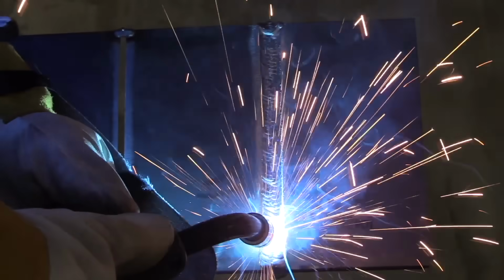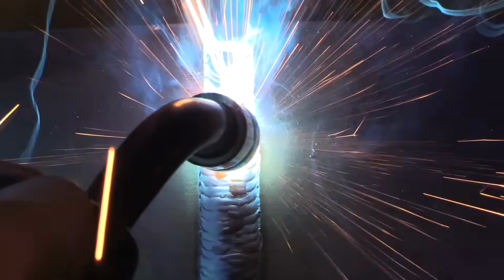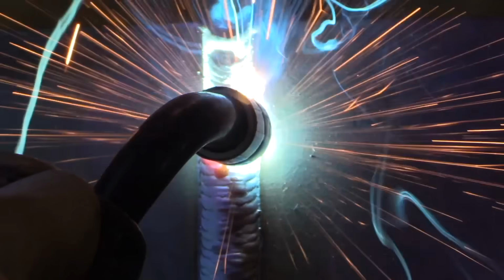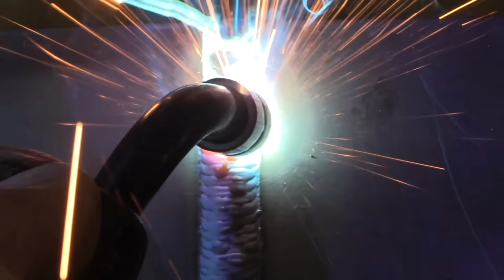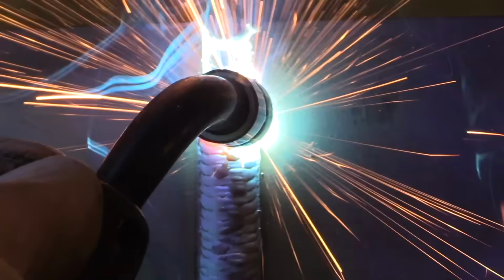But basically you're just scooting across the middle, not spending a lot of time, and pausing briefly on the edges and overlapping the edges of the bevel by only about a 1/16 of an inch, and then trying to progress evenly up the joint. And if you progress evenly and your timing is even, you're going to have a uniform cover pass.